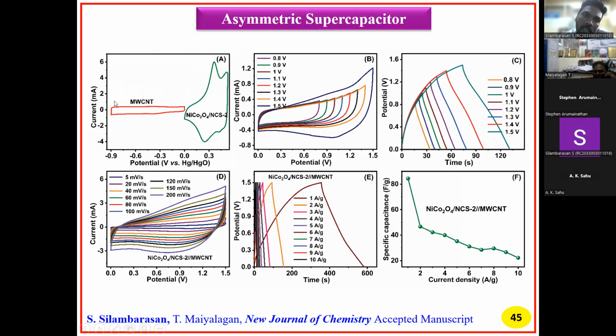Here, for the negative electrode we chose multiwalled carbon nanotube, purchased commercially. Next one, the nickel cobalt oxide with nitrogen doped carbon sphere, sample 2, was measured in CV from 0 to 0.55. For the multiwalled carbon nanotube, the negative potential is from minus 0.12 to minus 0.9.